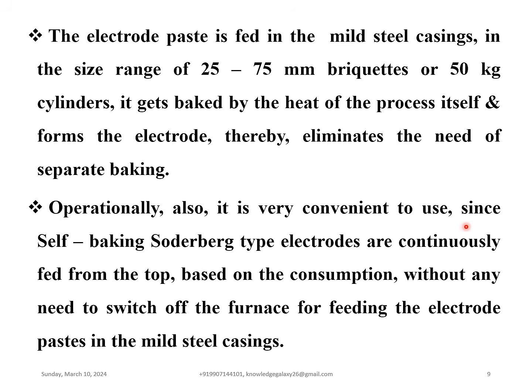The electrode paste is fed into the mild steel casings in the size range of 25 to 75 mm briquettes or 50 kg cylinders. It gets baked by the heat of the process itself and forms the electrode, thereby eliminating the need for separate baking. This is why it is called the self-baking Soderberg type electrode. Operationally also, it is very convenient to use, since self-baking Soderberg type electrodes are continuously fed from the top based on the consumption, without any need to switch off the furnace for feeding the electrode paste into the mild steel casings. So all these reasons justify the use of self-baking Soderberg type electrodes in submerged arc furnaces.